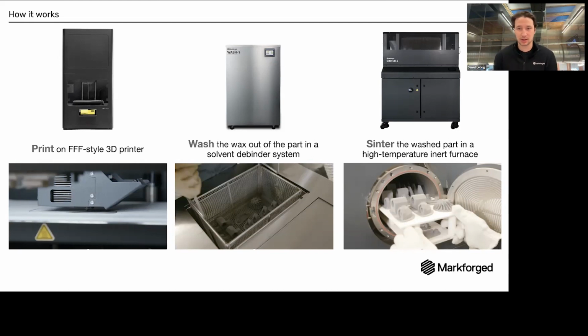And then the last step is sintering. Sintering happens in a furnace, and within furnace sintering, there are two stages. The first stage is an intermediary stage where we bring it up partway to temperature and we burn out the rest of the binder. During that burning out, the part actually shrinks a predictable amount. So the scaling up that we automatically do when we're printing shrinks away, and the resulting part out of the sinter is the correct size. Then after we burn out the rest of the binder, we raise it to nearly its melting point. That's when it turns from a bunch of metal powder pieces next to each other into an actual metal part. So that's the entire process.